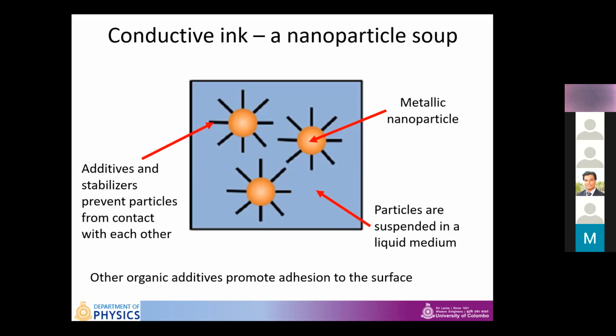They are suspended in a liquid medium, maybe water or any other organic solvent. The nanoparticles are decorated by using additives and stabilizers. Now, these additives prevent nanoparticles from contacting with each other before we put it down on a substrate. There are other organic additives as well to ensure the adhesion of the ink onto various substrate.